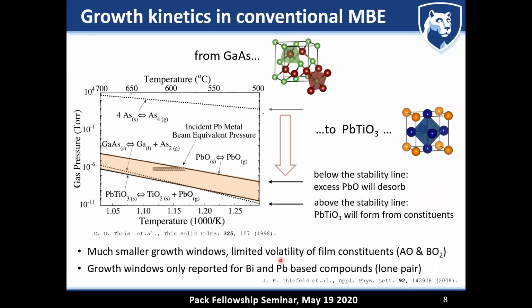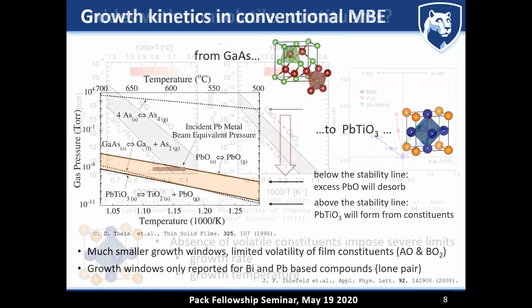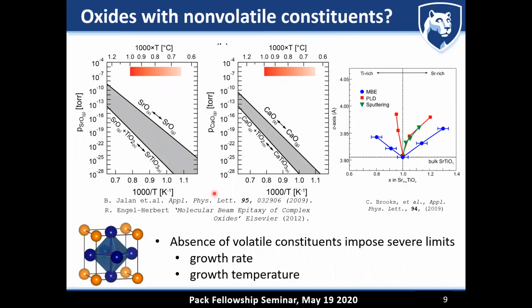All of this works. But now the question is, what is going to happen if you don't have a complex oxide that has a volatile constituent? And for those, you can actually calculate where the self-regulated growth window is going to be. And I'm showing you two examples here that were calculated. One for almost like the godmother of complex oxide materials. This is strontium titanate. And then this one is the growth kinetics for the compound calcium titanate, which is actually the one that gave the name to the perovskite family.